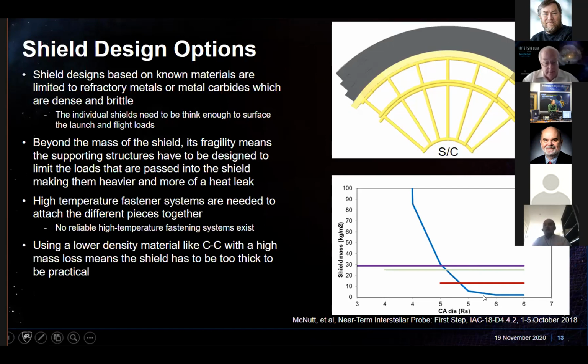Carbon, a good material of choice for mechanical properties and temperature stability, does have an upper limit where it disappears all by itself. So if you're just making the shield thicker and thicker to allow for that vaporization, eventually it becomes so thick that the mass goes up. These are kilograms per meter squared, and we're talking about tens to hundreds, and with a shield that's tens of meters square, you're talking about huge masses here. So again, something different needs to be done.